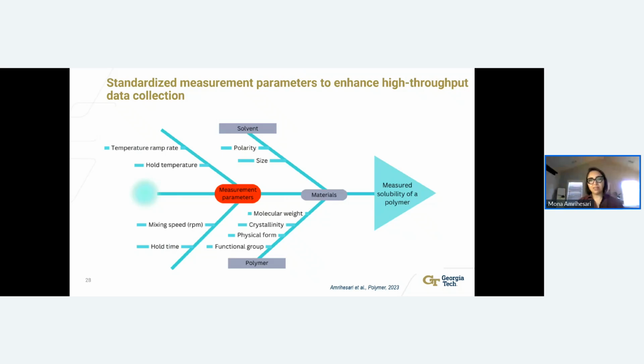So to design our process, this shows the fishbone diagram for looking at the final property of interest and some of the parameters that affect this phenomenon. We are here looking at the measured solubility of a polymer. And we have materials, solvent and polymers, and different characteristics of solvent and polymers are shown here that affect the solubility of the polymer, based on the literature or what we know. And we also have the measurement parameters, because we didn't know at the time how we could collect the data with Crystal 16 in a way that is meaningful across different behaviors of polymer solutions.